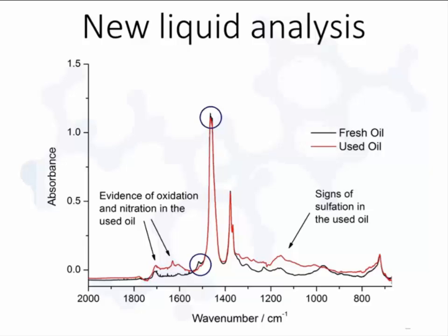So here are two spectra of different oils. Oil companies like BP or Shell will want to use spectroscopy to determine whether their oil's new or contains some contaminant, has it been oxidized. And in the black spectrum, I've got some fresh motor oil, and there are some quite clear peaks, for instance, the ones at 1350 wave numbers and just under 1500.